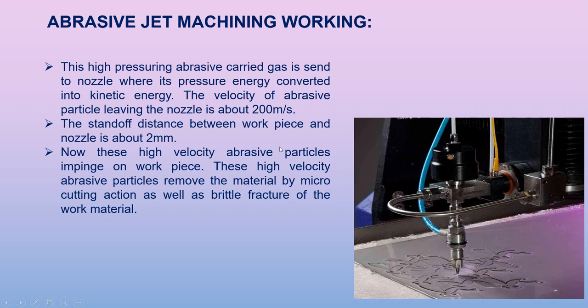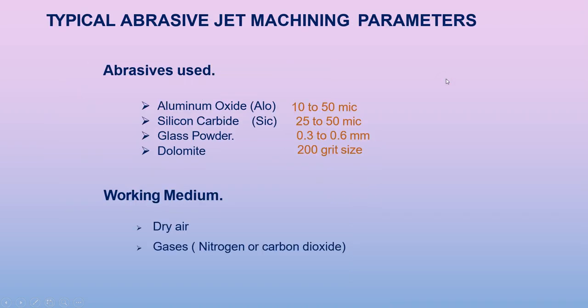So the standoff distance between the workpiece and the nozzle is about 2 mm. So the standoff distance between the workpiece and the nozzle should be 2 mm. Now, these high velocity abrasive particles impinge on the workpiece, and these high velocity abrasive particles would remove the material by micro cutting action, as well as the brittle fracture of the working material.